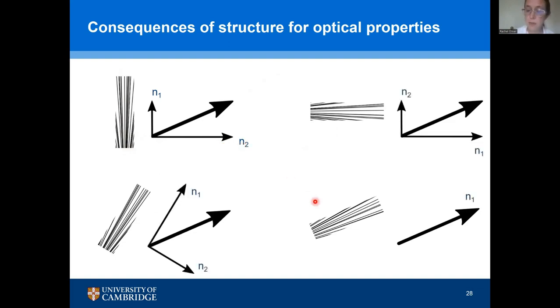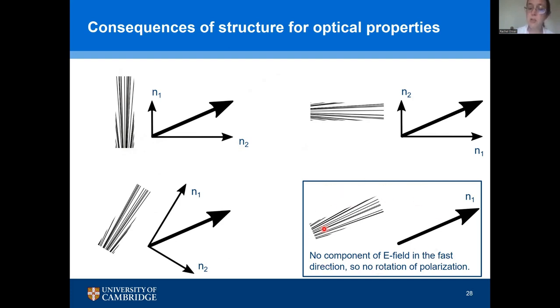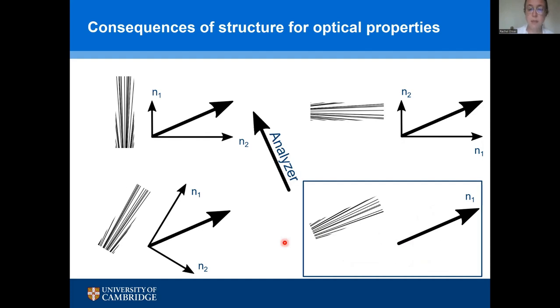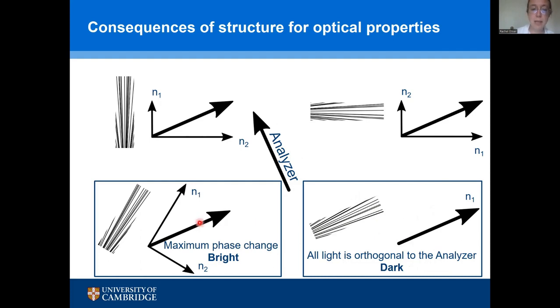But if we look at this orientation down here, where the direction of the polarization is parallel to the direction of the pores, the light only experiences one of those refractive indices. So that means that because there is no component of the light resolved along the second refractive index, there'll be no rotation of the polarization. Whereas at an angle, this will work. So that means that if we bring in the analyzer, this region will seem dark because the light's rotation doesn't change, okay? Whereas if we have an angle like this, where we're sampling both of our two refractive indices with our polarized light, then we'll see a large phase change and the material will appear bright.